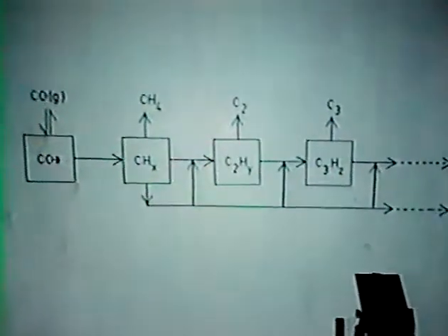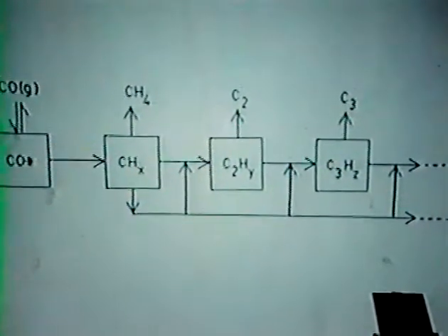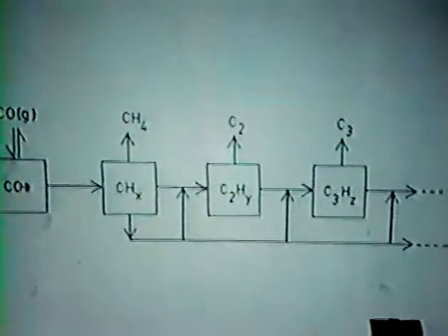Most of the evidence that one can find for nickel chain growth would indicate that the quantity of chain fragments which are held on the surface is very small, unlike what we heard earlier about ruthenium, where there seem to be bigger quantities of these growing chains held on the metal surface.